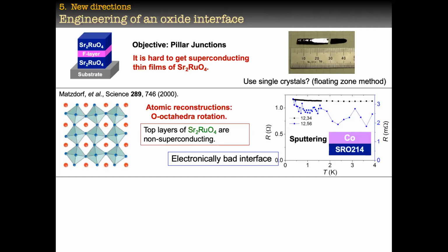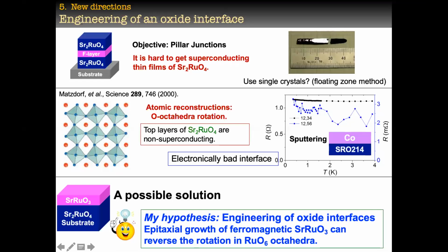The problem is that this material has atomic reconstructions. Reconstruction means that the crystal reconstructs itself along the ab plane with a rotation of the oxygen octahedra, which breaks the superconductivity. I checked it by putting cobalt on top of it, deposited by sputtering, and you can see there is no superconducting transition. Then we need to think of something different.